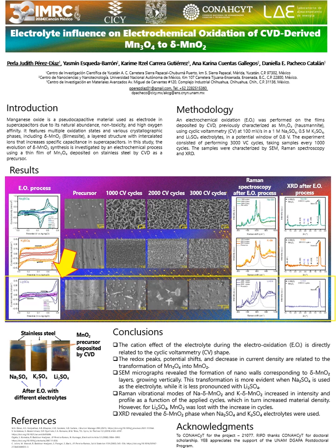Now, for lithium sulfate, the effect was different. The CV shape presents two pairs of redox peaks, one around 0.45 volts and the second around 0.73 volts. However, the increase in current density in the capacitive region is minimal compared to the other two electrolytes. This is reflected in the micrographs, where only a slight formation of nanowalls is observed, and by 3000 cycles